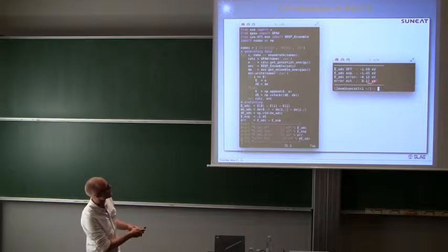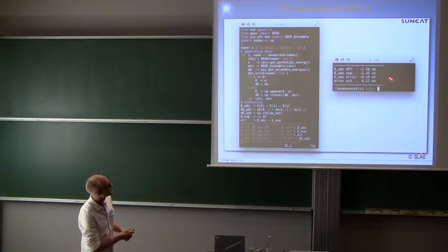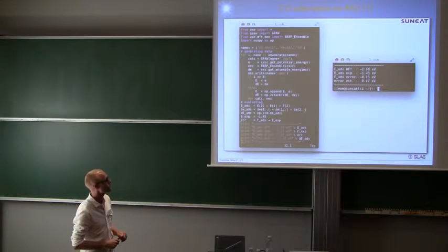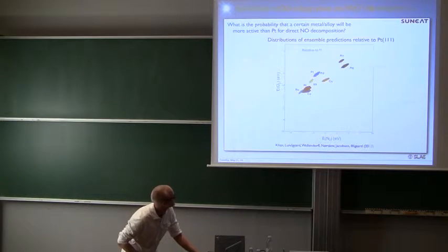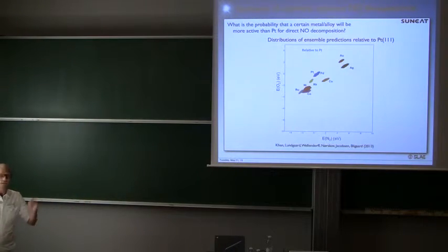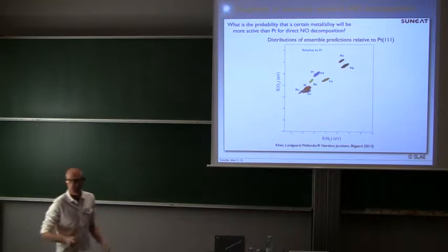And this is then what it looks like when I run this script. So my DFT calculation predicted 1.6 eV, which is off by 0.15 eV, and the error estimate turns out to be 0.17 eV. So that's all fine, I would say, because that's just one single calculation, and then you say, okay, it's not accurate, or it's not exact, which you knew already.